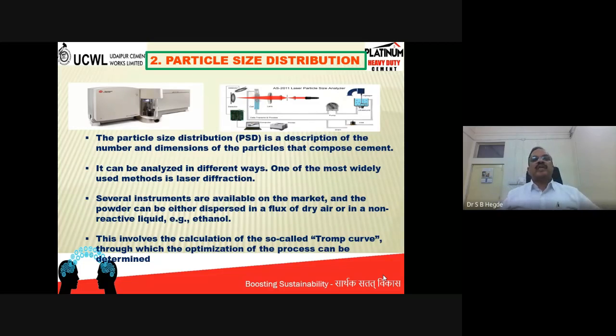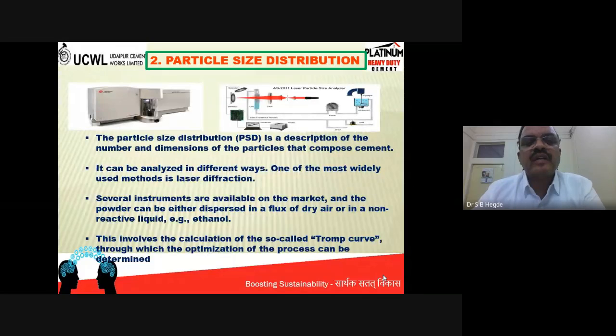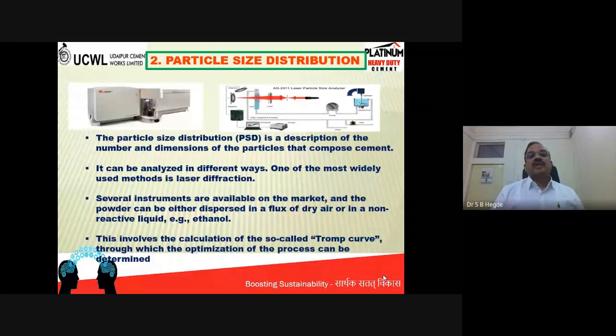And I mentioned the particle size distribution of the cement because, as you are all civil engineers, you know its importance for strength development and other rheological properties of the concrete. So in the cement plant, as I mentioned earlier, we are targeting 3 to 32 micron particle size. Higher is better. If it is coming at 70%, it is excellent. If it is 72%, it is still more excellent. If it is less than 50%, which is a danger mark, we have to improve upon it.